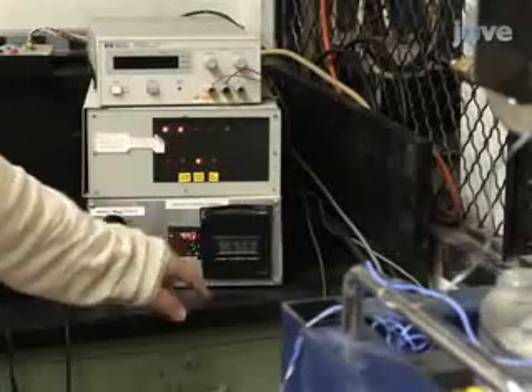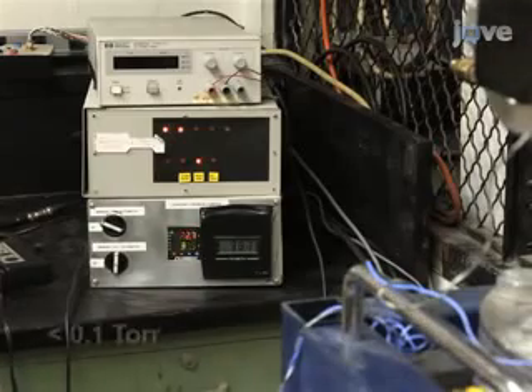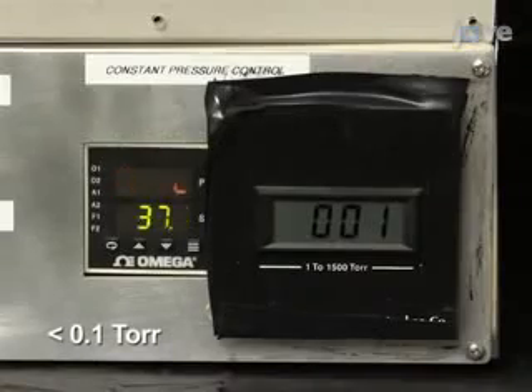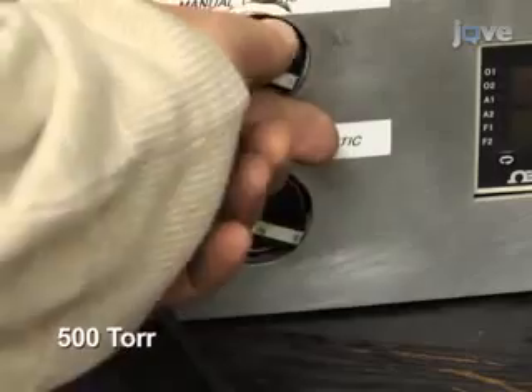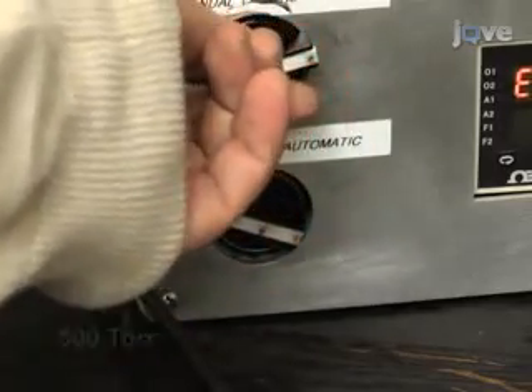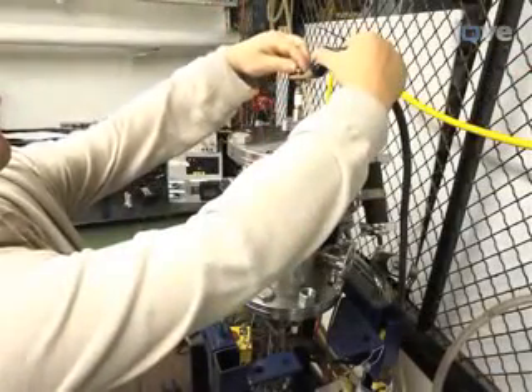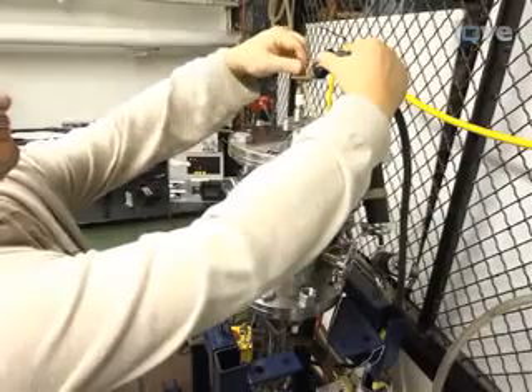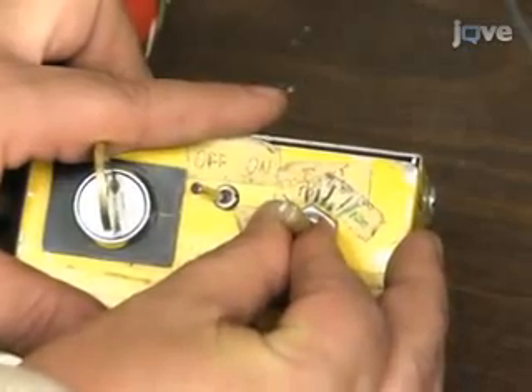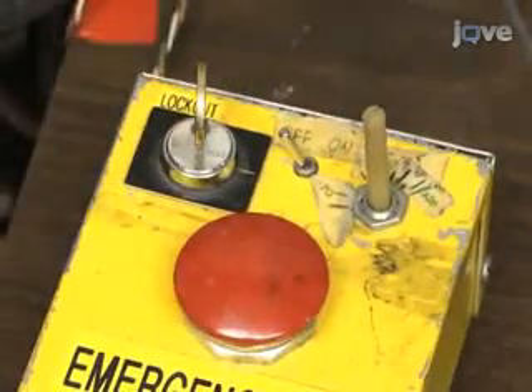To ignite the arc plasma, pump down the cylindrical chamber to a pressure of less than 0.1 torr of vacuum and then fill it with helium to 500 torr. Connect the arc electrodes to a DC welding power supply and set the power supply to an arc current of about 75 amps.